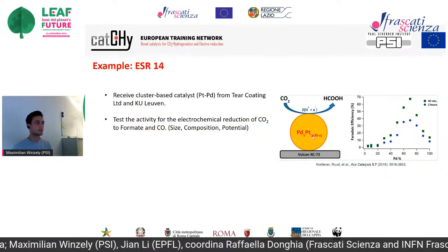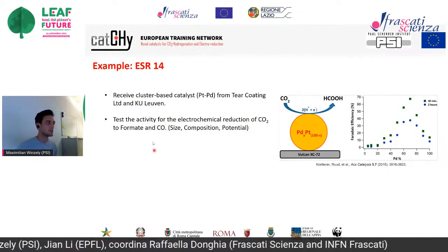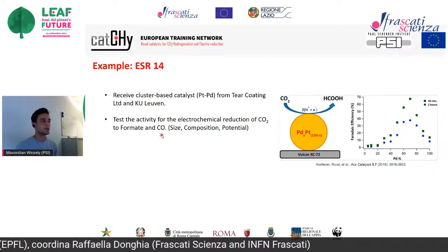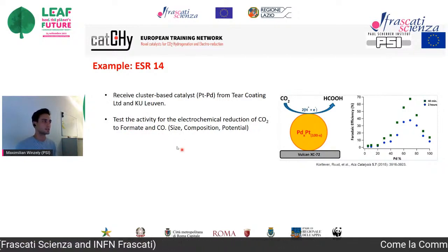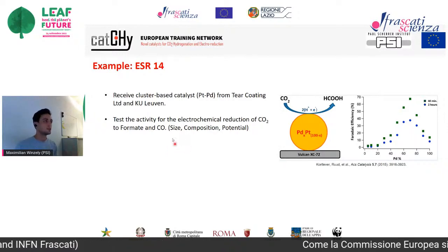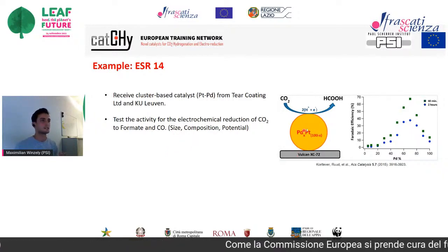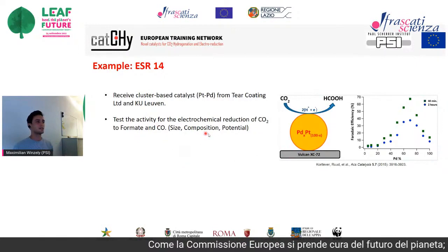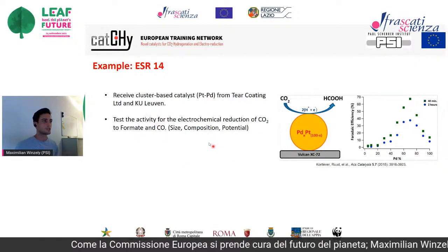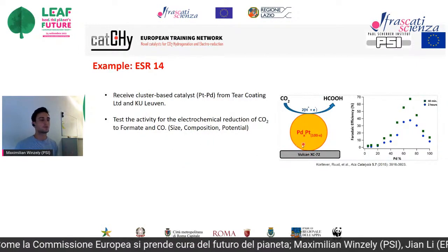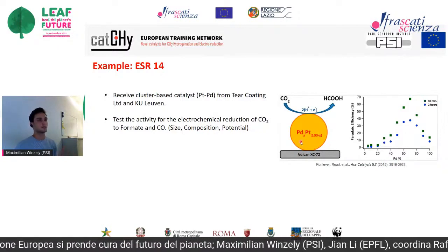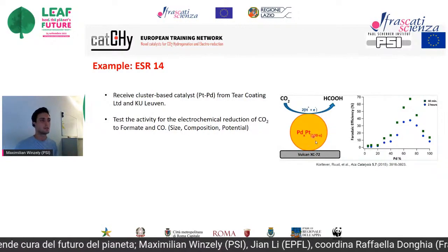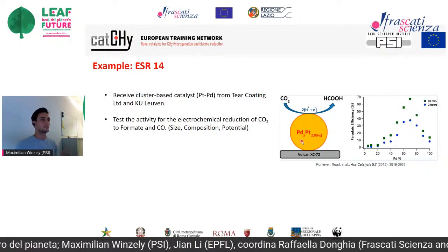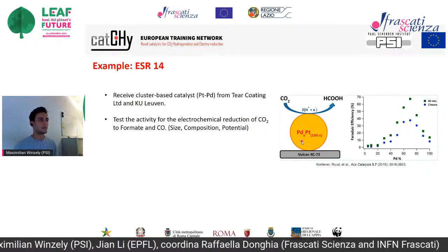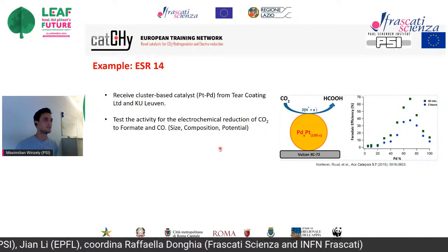And when I receive the clusters, I will test them for their activity for the electrochemical reduction of carbon dioxide, especially to products such as formate and CO, because studies have shown these are the most economically feasible products. And then of course I will look at how the size of these clusters can affect the activity, and also how the composition can affect it. For example, I will look at bimetallic clusters, consisting of palladium and platinum, and I want to see how, for example, a higher palladium content can affect activity.